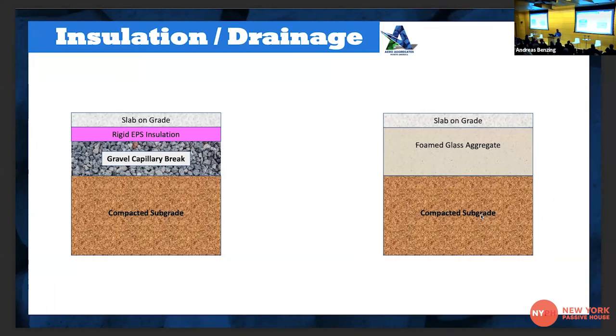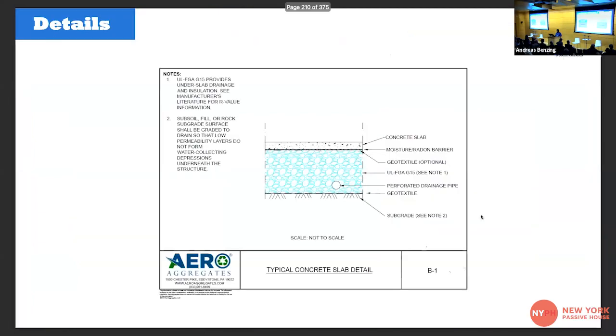Typical detail: slab on grade, a couple inches of rigid foam insulation, and then your gravel capillary break. No more; you can just put down the foam glass. Typically, I'm specifying to architects 15.5 inches. The material has a compaction factor of 1.25. You place 15.5 inches, compact with a plate compactor, and you end up with 12 inches. Those 12 compacted inches get you the R-1.68 per inch. No need for natural aggregates.